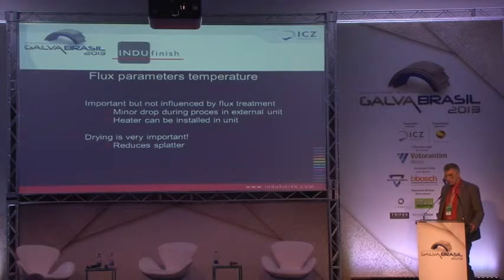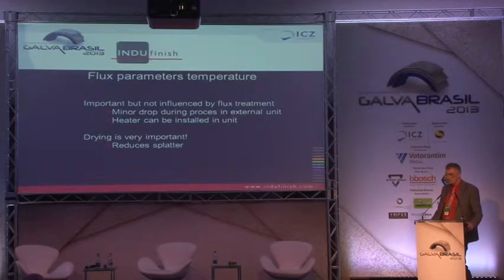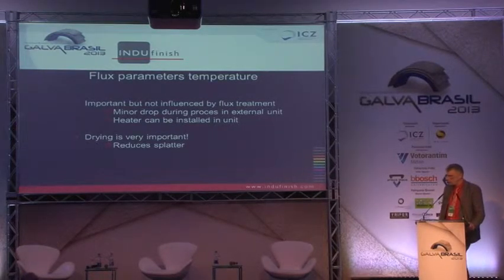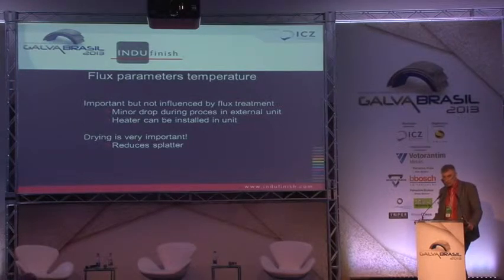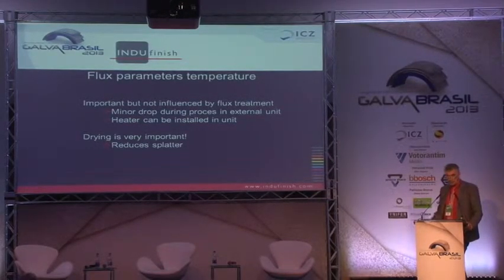But what is important is that you make sure that your flux product is dry when you enter it in your kettle. I'm sure everybody knows, but drying is very important. It reduces splatter. Most plants in Europe are using a dryer, which means the flux temperature is about 40, 45 or 50 degrees. If you don't have a dryer, I think you have to move your temperature up to 70 or 80 degrees.